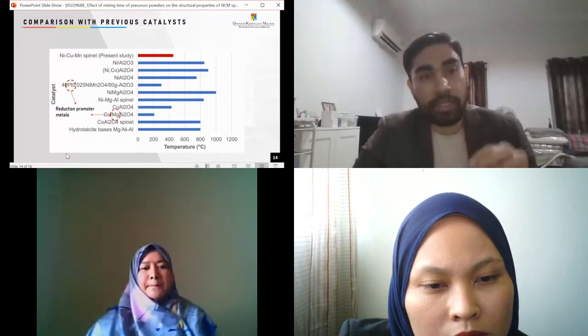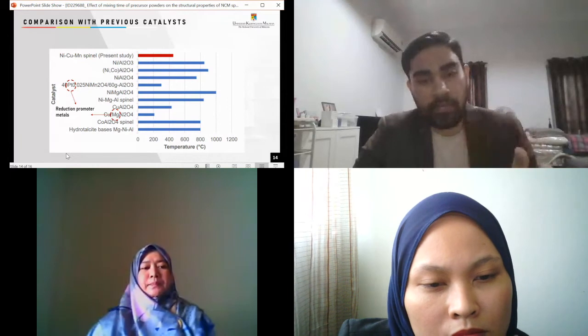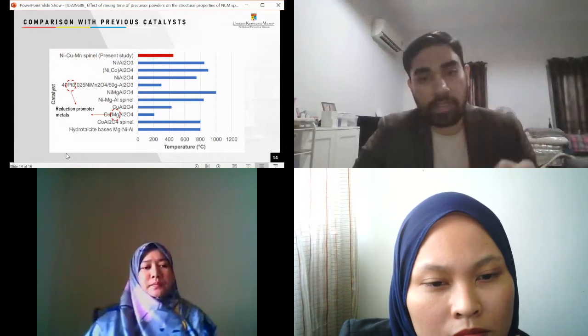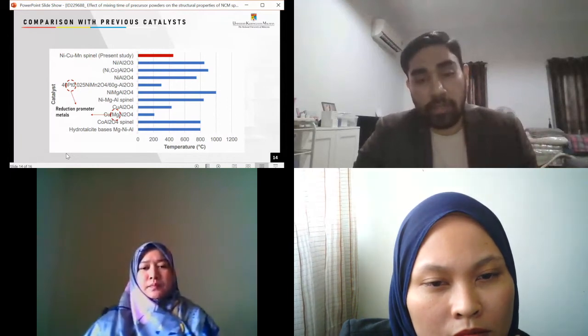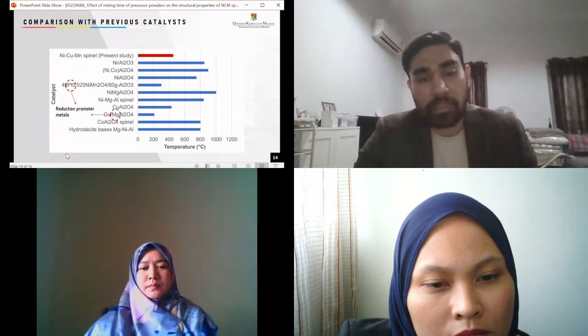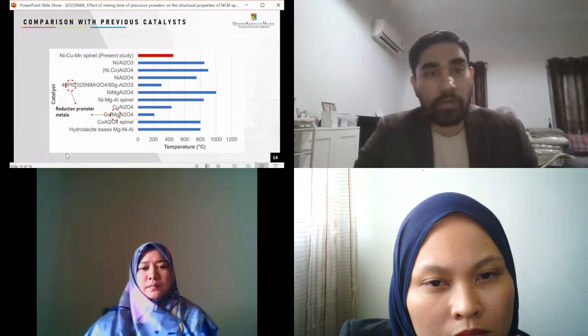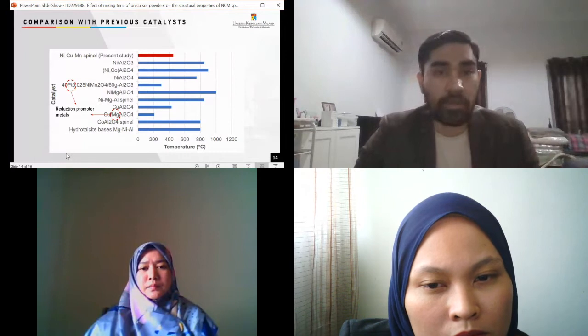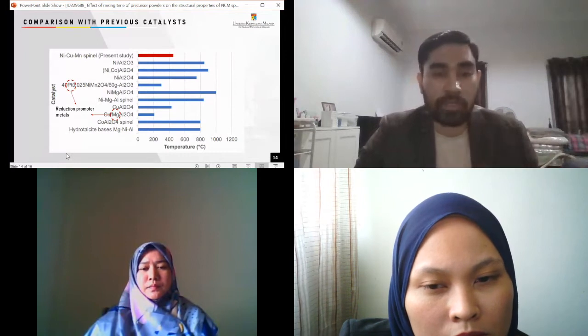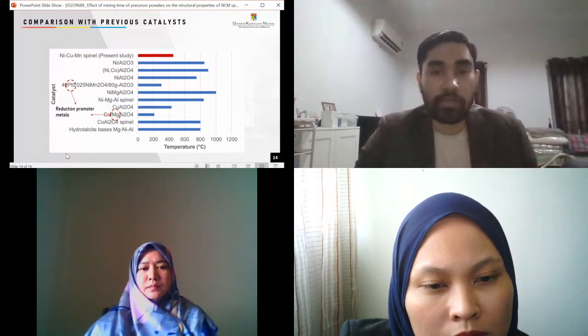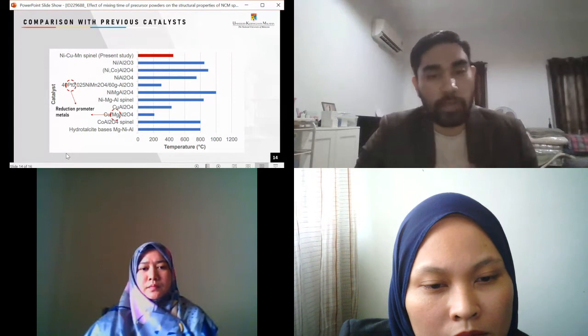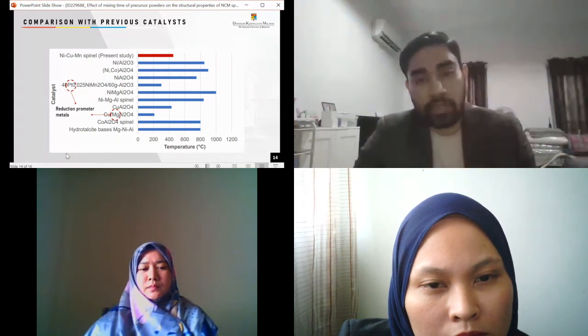However, we determined that the present study is already enough for solid oxide fuel cells, because the solid oxide fuel cell operating temperature is around 600 to 800. Therefore, the reduction temperature is already lower than the operating temperature of the solid oxide fuel cell, which means the spinel is already enough to be used for solid oxide fuel cell application.